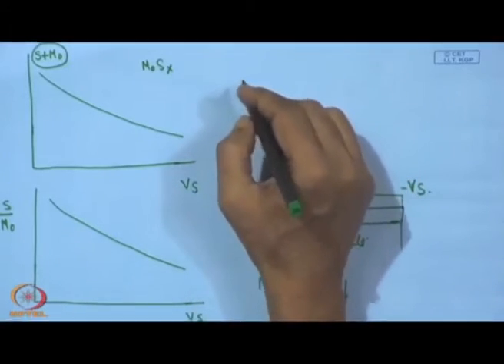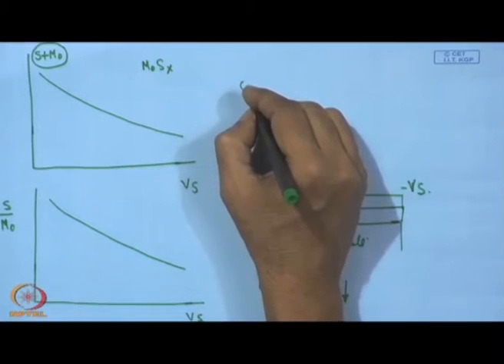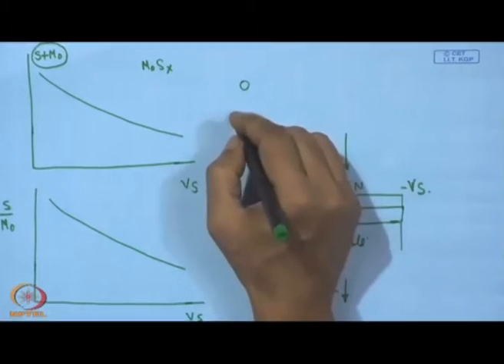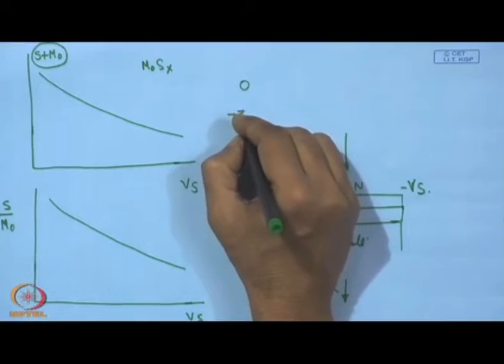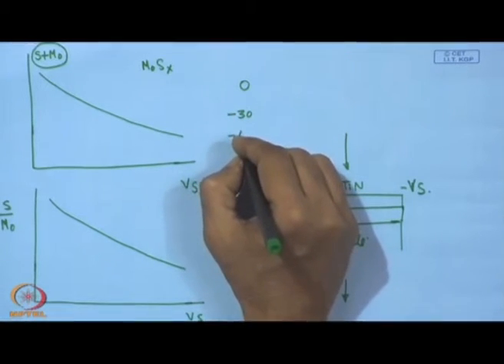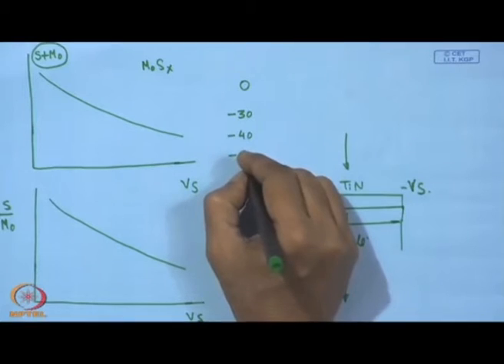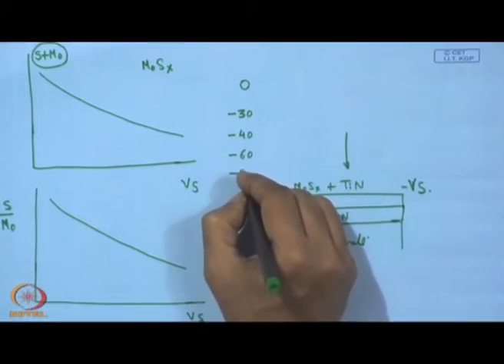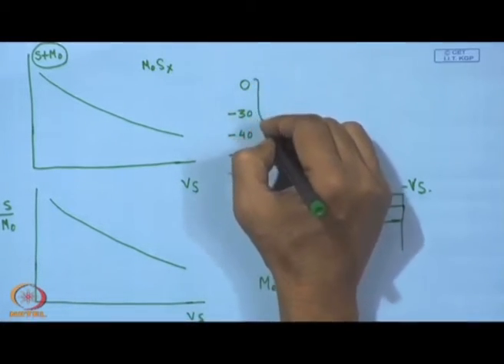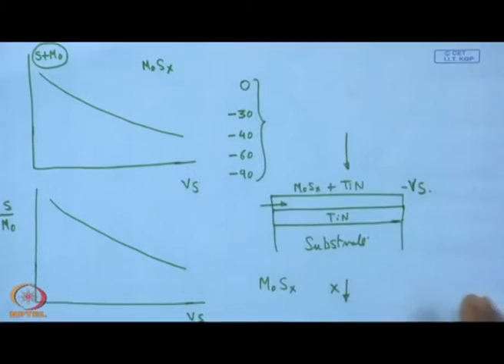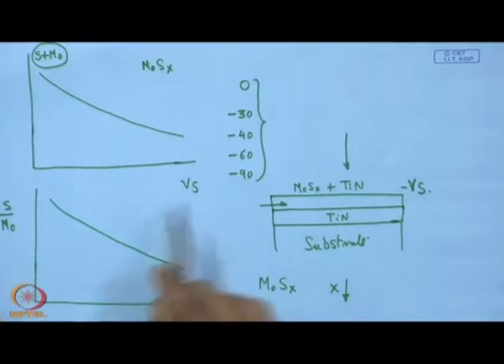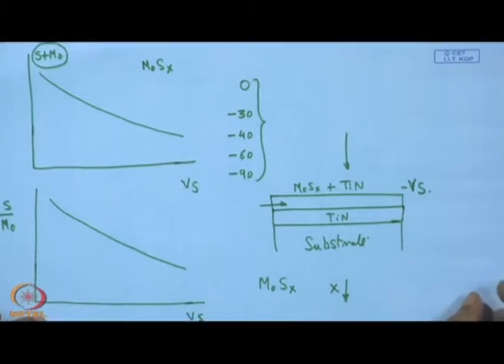So, normally, if one considers increasing bias starting from 0, say it is minus 30, minus 40, minus 60 and minus 90, this is a range. So, if one tries to examine the effect of the substrate bias voltage, one should have such kind of variation with increase of bias voltage.